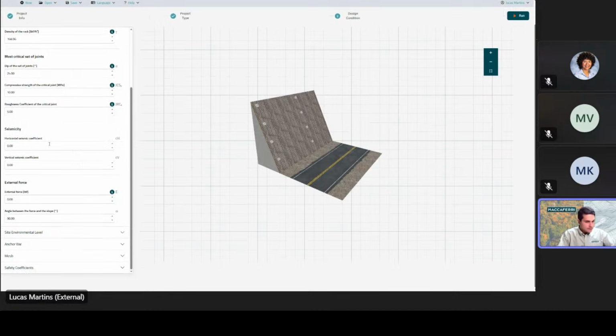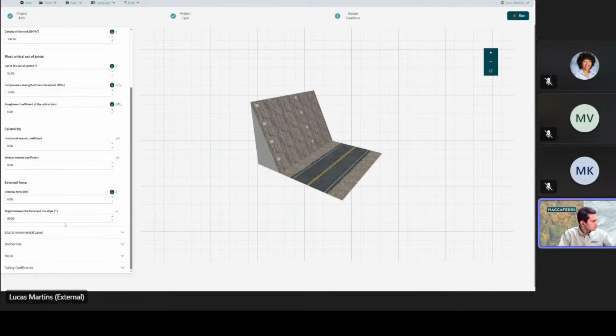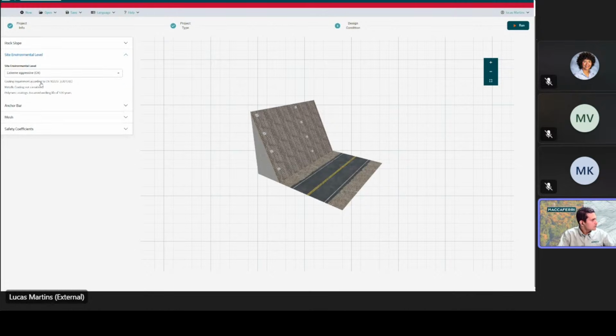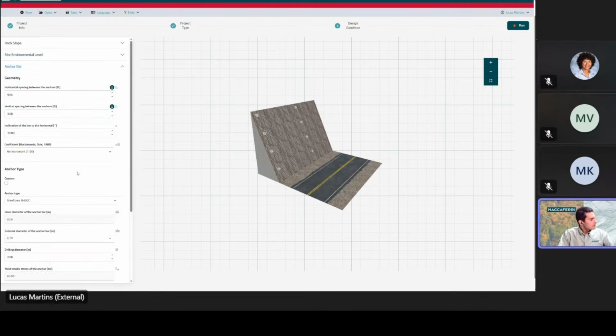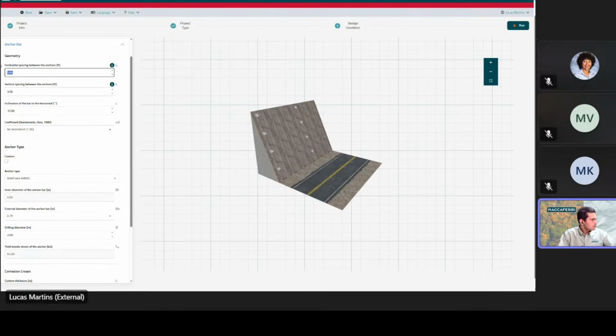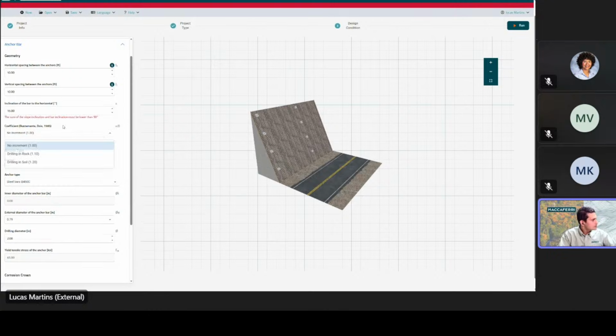For this system, since it provides stability to the slope, you want to enter your seismic coefficients. On external forces, if you want to account for ice or snow buildup, you can do that. It would create a shear force on the nails or anchors. Again, there is the environmental level for the corrosion protection. Now you have the characteristics of your anchor bar. It's very similar to the simple drapery, but now you have horizontal and vertical spacings. Let's try a 10-foot by 10-foot pattern. Here you have the inclination of your bar to the horizontal. Again, as I showed, depending on the inclination the bar can act in shear or in tension, so you always want to shoot for a tensile resistance.